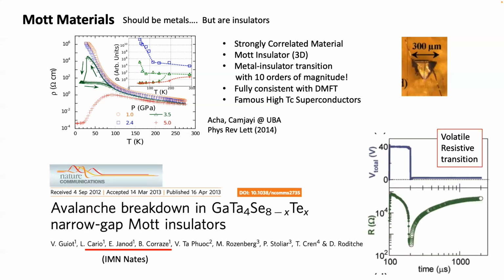Okay. But coming back to what we do, this material has been fabricated by this group of colleagues in Nantes, and they were applying strong electric fields to it. So you apply a strong electric field, and what you observe is that the resistance of the system suddenly collapses. When the applied voltage goes away, it recovers to the original value. That is why it's called a volatile resistive transition. And you can repeat this thousands of times and you get perfect agreement in the data. There is no variation. This is a genuine feature of the system.